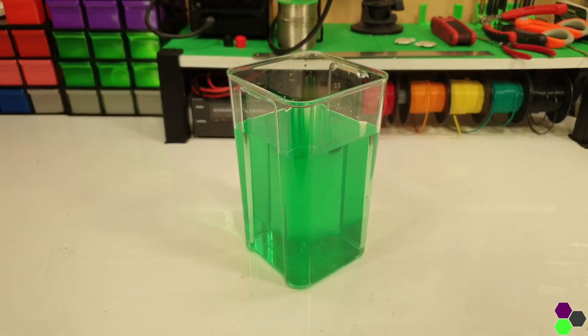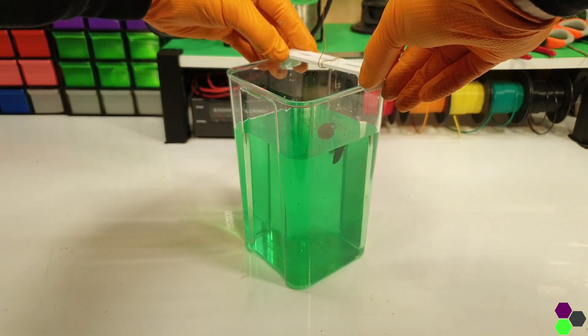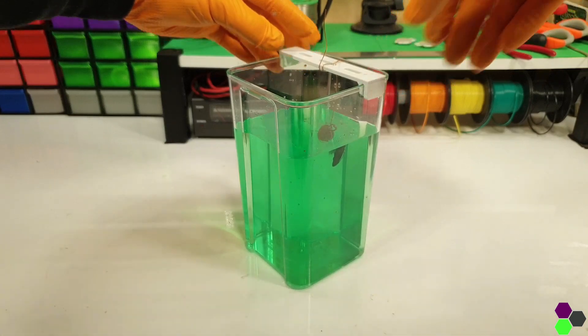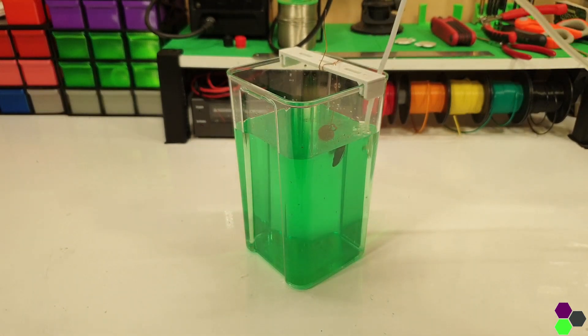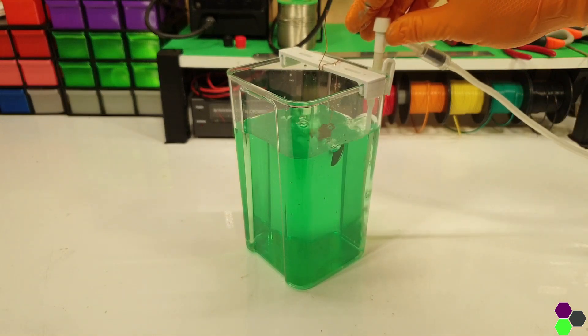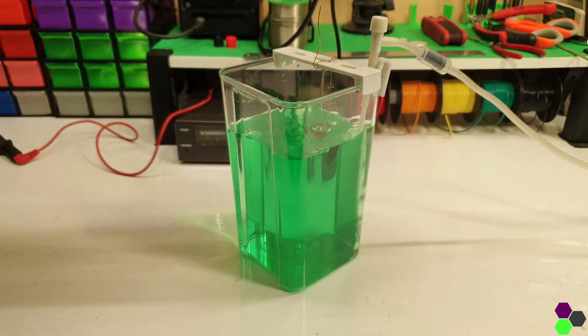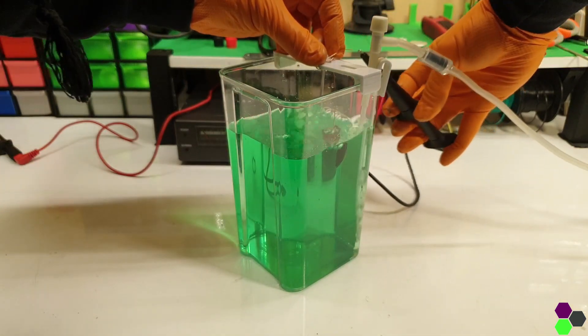For most small parts the easiest way to plate them is in an electrolyte bath. You can do this by lightly wrapping the part in some wire and suspending the part in an electrolyte solution. Agitating the electrolyte will help you get a uniform coating of metal around your object and will reduce the likelihood of your part burning. You can do this by hand, either by moving the part around or stirring the electrolyte. I use an aquarium pump so I can leave the part unattended for extended periods.